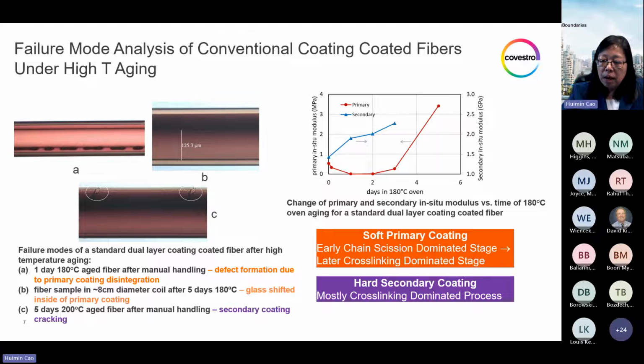Right. And remember, these are accelerated lab tests at temperatures much higher than your application temperature. So at your actual application temperature, there might be a long period of time when the coating has broken down into a gel-like material. This is the most risky situation in the field, because the primary coating at that stage has a high risk of forming cavities and developing delaminations, which will cause attenuation increase. And you definitely don't want to see that.